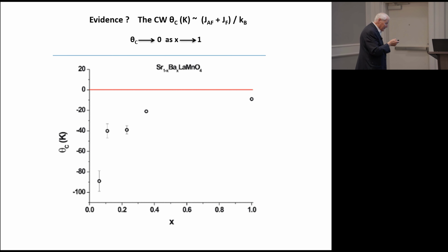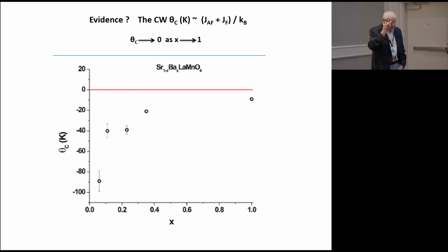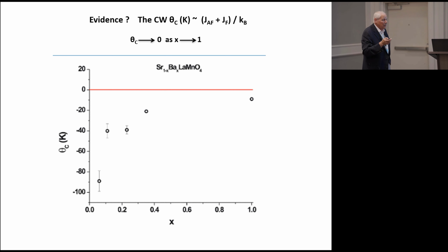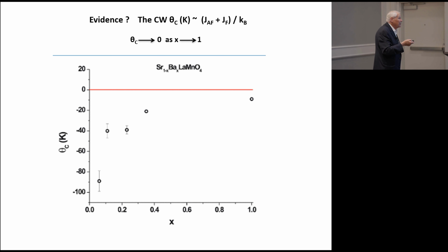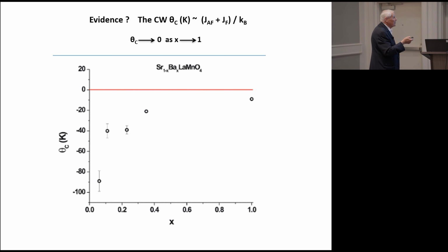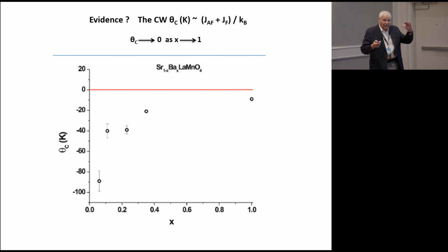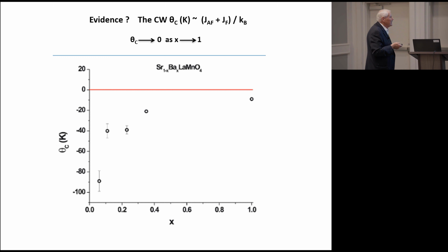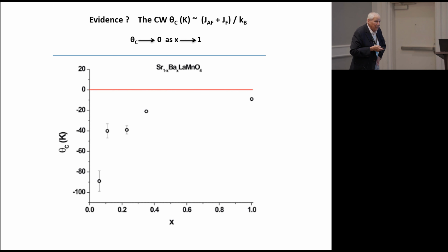There's some evidence for this. If you measure the Curie-Weiss intercept of the inverse susceptibility curve, in principle this is sort of an algebraic sum of all the exchange interactions, and you have an antiferromagnetic and a ferromagnetic exchange interaction. If the all strontium case is strongly antiferromagnetic, as you go to the barium case, the theta value begins to approach zero. And so we take that as proof for our hypothesis.